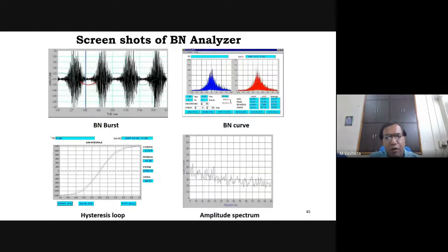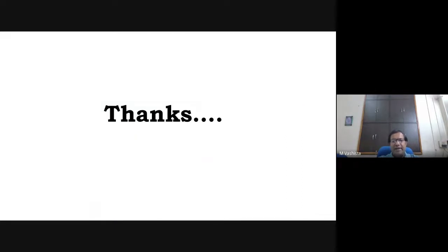These are screenshots of the Barkhausen noise analyzer. You can see the hysteresis loop, hysteresis loop properties, RMS, peak value, and peak position of the Barkhausen noise signal, and they have a direct correlation with the mechanical properties. So we can characterize the material using this magnetic technique, and that is very much popular. Nowadays it is an emerging technique. This technique is available in India at BARC Mumbai. IIT Kharagpur also has this technique. Our institute has recently procured this technique.